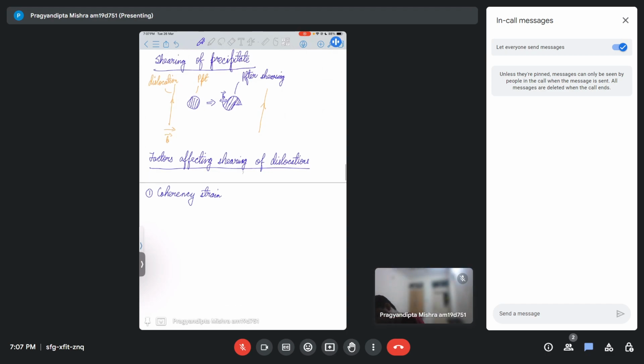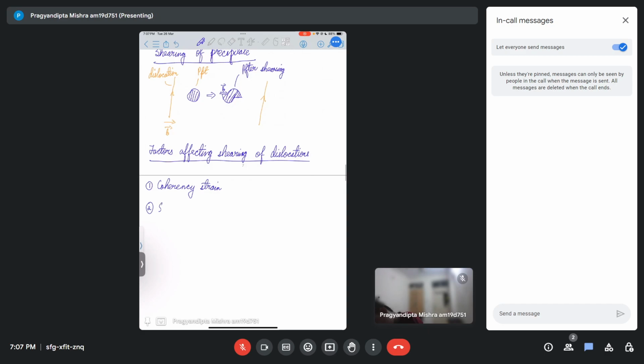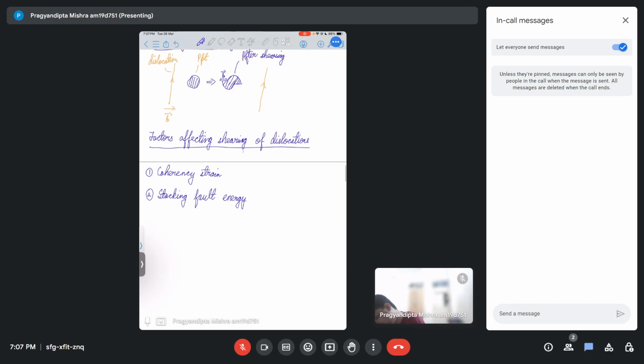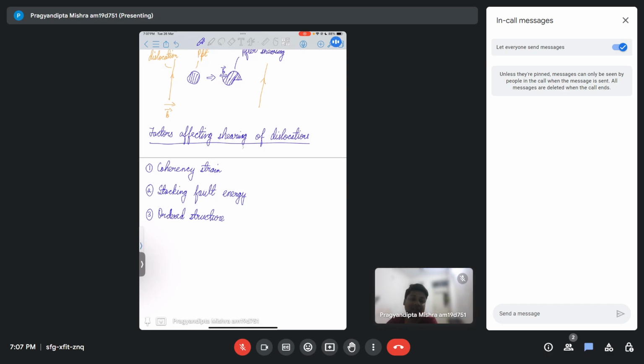Okay. Secondly, stacking fault energy. Again, very important. If there is a presence of stacking fault, because if you have certain particular types of dislocation, you will have stacking fault. So whether those stacking faults are present or not will also influence how the cutting would be. Okay. Third is if the structure is ordered or not. Very important, because if the structure is not ordered, then the dislocation motion would be affected by it, and then the shearing process also will be affected to an extent.